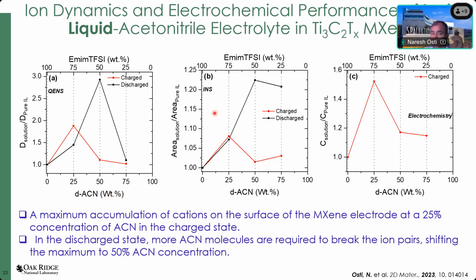Now, a similar type of maxima for the charge state and the discharge state was obtained if you take the normalized intensity from the inelastic neutron scattering, and the same goes for the capacitance. You see, there is always a maximum at a particular concentration. That means this concentration is somehow the optimum concentration at which the maximum number of ions attach to the surface of the electrode.